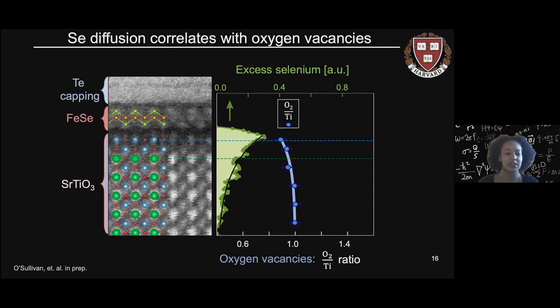In addition to this, we're able to quantify the amount of oxygen vacancies. So we can take this one step further, and by analyzing our oxygen and titanium signals and the ratio between the two, we're able to take this ratio to be our unit of oxygen vacancies and compare it directly with our selenium diffusion. So we can quantify the oxygen vacancies at the top layer of titanium to be approximately 11%, and at the second layer of titanium, I should say, to be approximately 5.5%.